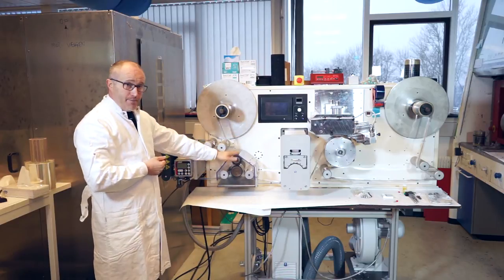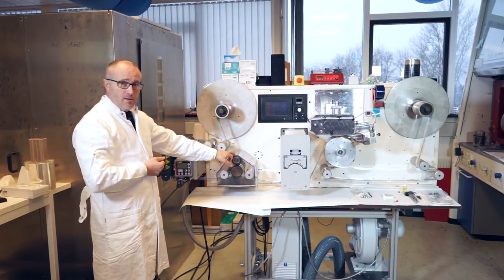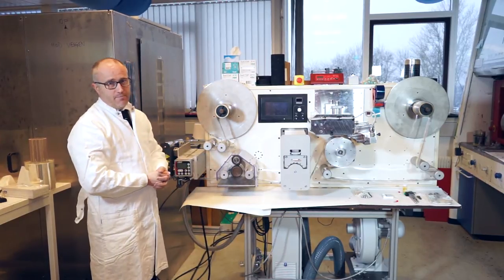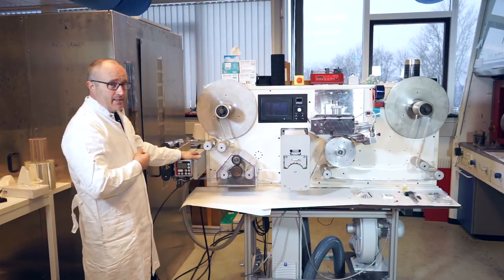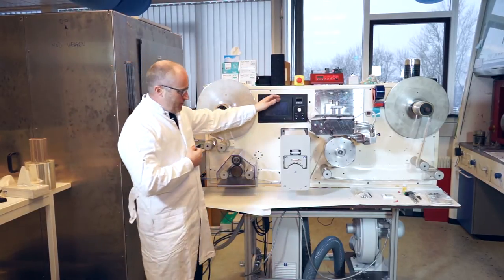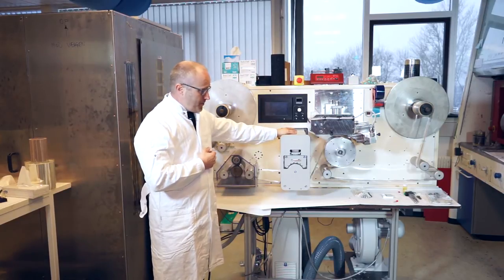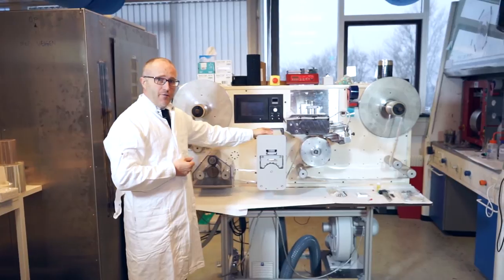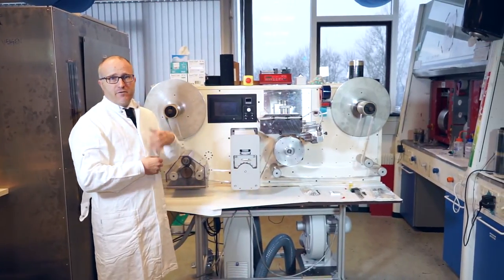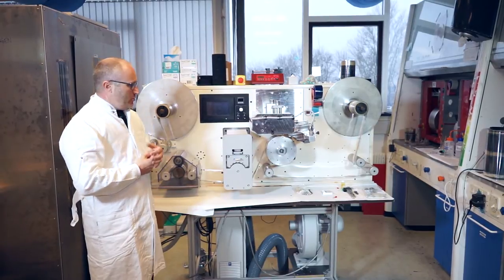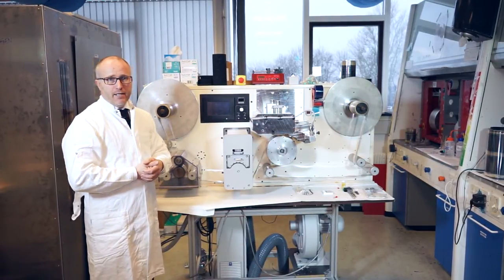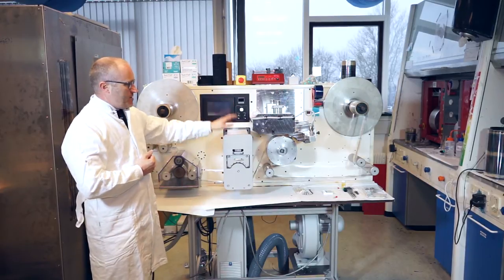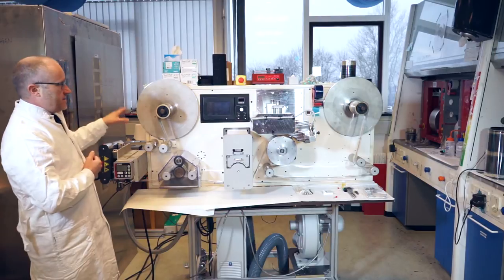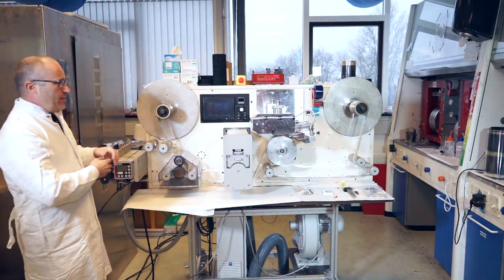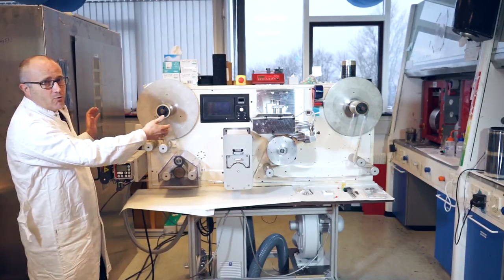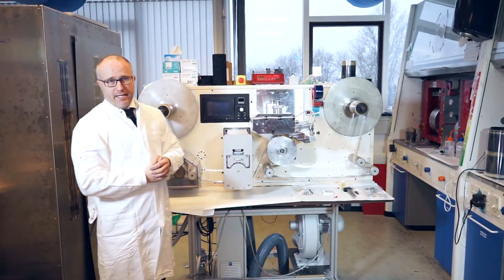This is handled in this case by a nip. So it's a driven roller and a rubber counter roller that simply control the foil transport. So not only do we have an edge guide, we also now have a nip. Maybe you also need to condition the surface. In this case, it's a corona treater. So you have a plasma that oxidizes the surface. For instance, if you have inks with a higher surface tension, you need maybe to oxidize the surface slightly to wet better during drying. So then you also have this option. So this is three new things, four actually, if you count the unwinder and the rewinder, four new things that we didn't have to think about on the mini roll coater. So it's already horrendously increased in complexity.